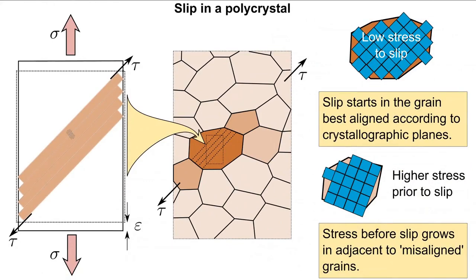What we just looked at was for a single grain with a single orientation. We know that grains can have all sorts of crystallographic orientations due to how they solidify. Metals are almost all polycrystalline. For these circumstances, what happens is that slip will occur first in a grain which is best oriented with the plane of principal shear. Other grains with favorable crystallographic orientations that are further away from the plane of principal shear will slip with a higher apparent uniaxial stress. There is a second factor which polycrystalline materials encounter. Dislocations move to grain boundaries and cannot translate over to subsequent grains for the same reason, a lack of coincidental crystallographic orientations.